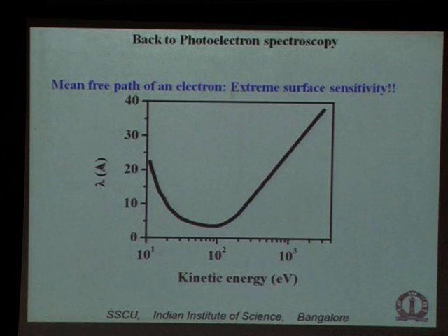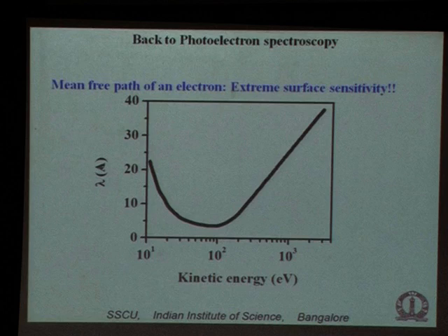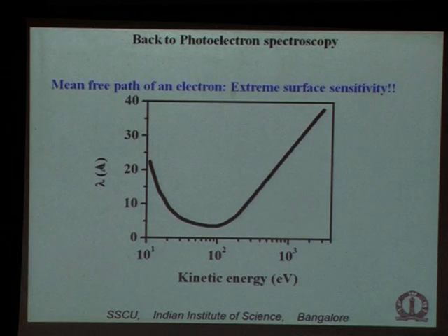And the surface electronic structure can be very different from the bulk, precisely because the periodic structure of the bulk gets violated at the surface. Surface has many differences from the bulk. So when you are interested in the bulk electronic structure and using electron spectroscopy, you have to be careful. In fact, this is one of the reasons why people have developed photoelectron spectroscopy to operate with very low kinetic energy and very high kinetic energy, by using very low photon energy and very high photon energy. These are the more recent developments so that you can look deeper inside the bulk.